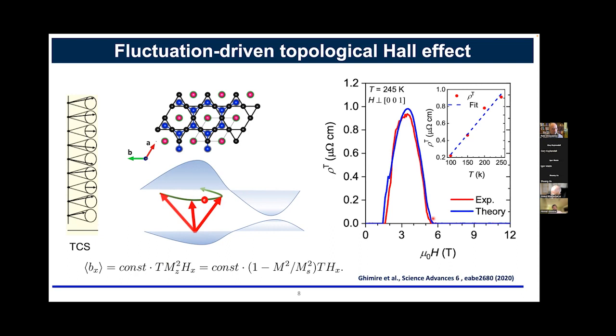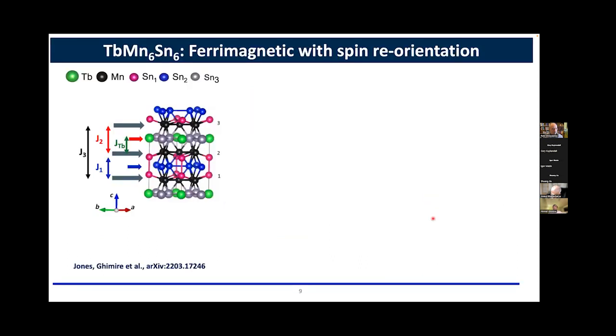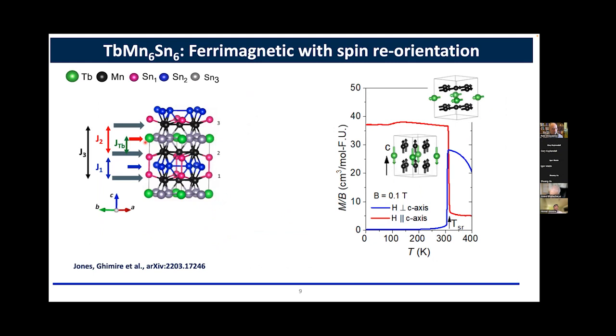Now, next, I will switch gears and talk about the terbium manganese 6 tin 6 compound. In terbium, instead of yttrium here, which was a nice system because the magnetism was coming only from manganese, we have terbium, and it complicates the exchange interactions. And this complication now brings about a very nice feature in the magnetization of this material: there is a spin reorientation. At high temperature, as in yttrium manganese 6, both the terbium and manganese moments order in the plane. And when you lower the temperature, they move out of plane. And that generates this spin reorientation transition at about 310 Kelvin.